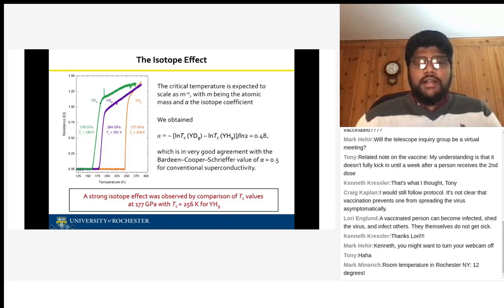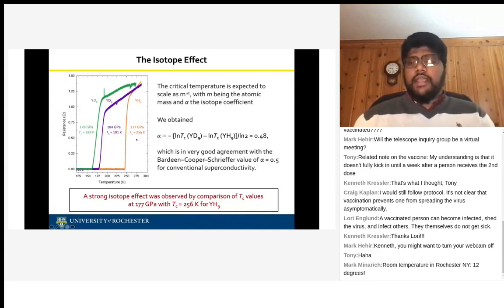And this is at 184 GPa, this is at 178 gigapascal. At the same conditions, same pressures, yttrium hydride, yttrium with the hydrogen, has a transition temperature of 256 Kelvin. So if you add deuterium instead of hydrogen, your transition temperature reduced from 256 to 183 Kelvin. So indicating that this is really a superconducting transition.